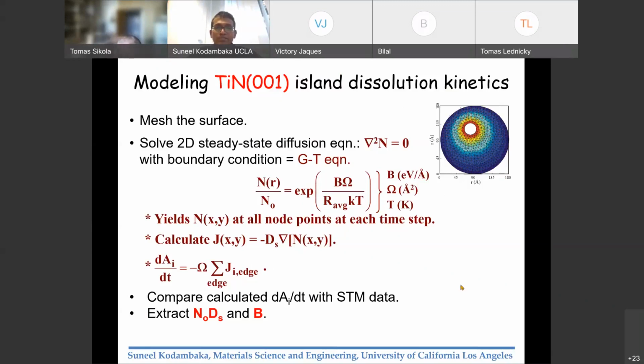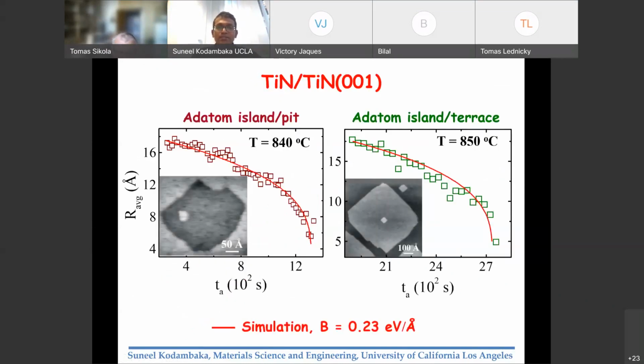The only two parameters in the model are the surface diffusion parameter and what I'm going to call a step energy parameter B, which is a measure of the step formation energy, and I'll come to it in a few slides. So using the modeling, we can accurately explain the observed behavior, and from the fits, we can extract the step energy parameter, which turns out to be 0.23 electron volts per angstrom. It is proportional to the step formation energy, but it's not the step formation energy yet. I'll come to how to extract that soon.